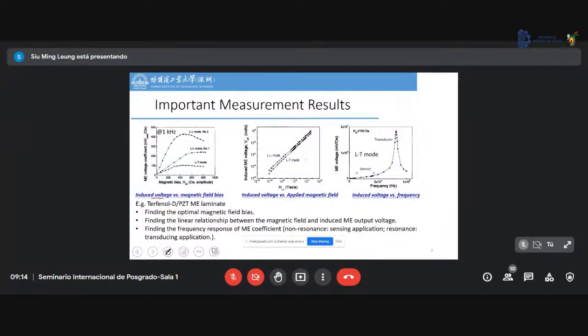Here we take one combination as an example: Terfenol-D for the magnetostrictive material and PZT for the piezoelectric material. Three diagrams are very important. The first one shows that when we apply different bias on the material, we get different electrical voltage output. The second one is about the linear relationship, because we want to use this material to fabricate sensors, so linearity is very important. The third one is the frequency response. In the low frequency region, we can use this material to fabricate a sensor. And at resonance, we can use it to make a transducer.